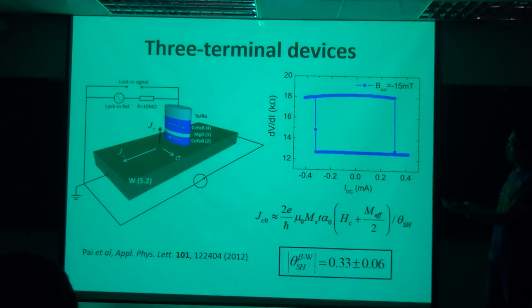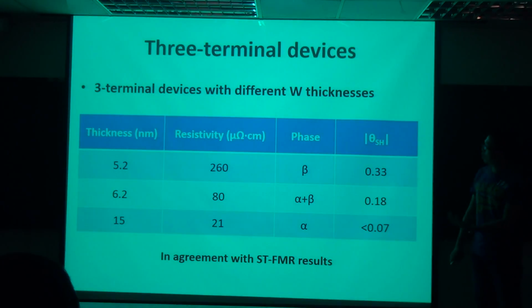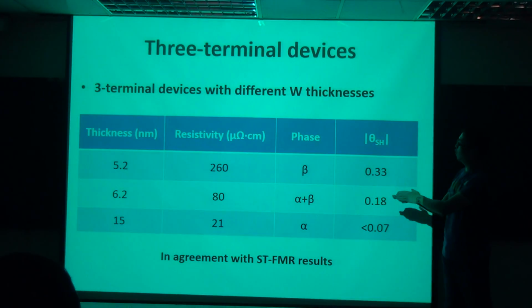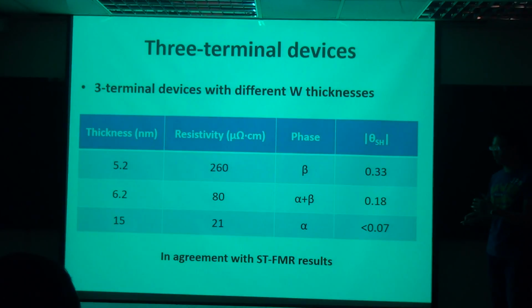And so since we did the FMR measurement, I decided, why not just pattern them again into three-terminal devices, and you can see even cleaner switching from this three-terminal device. And from that, we can also estimate the switching efficiency. It's also about 30%. And from those devices, from the switching, I can also estimate the resistivities and also the spin-Hall angle. So this phase or resistivity dependence of the spin-Hall angle is in good agreement with ST-FMR.